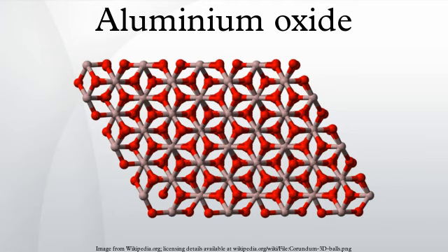A number of alloys, such as aluminium bronzes, exploit this property by including a proportion of aluminium in the alloy to enhance corrosion resistance. The aluminium oxide generated by anodizing is typically amorphous, but discharge-assisted oxidation processes such as plasma or electrolytic oxidation result in a significant proportion of crystalline aluminium oxide in the coating, enhancing its hardness.